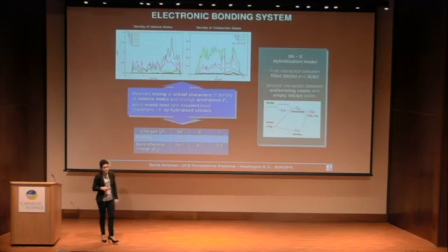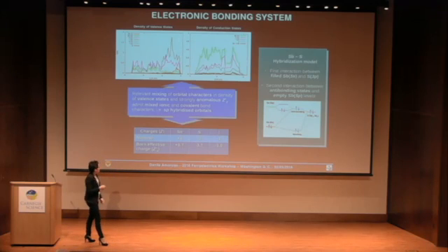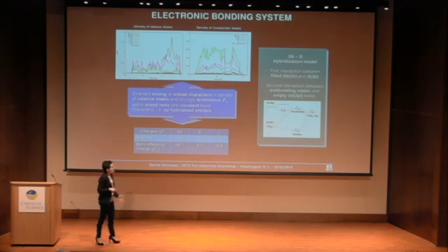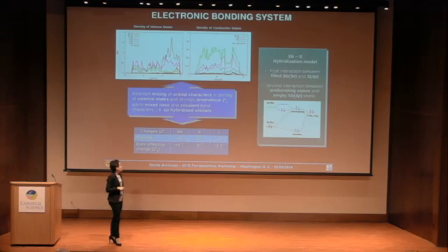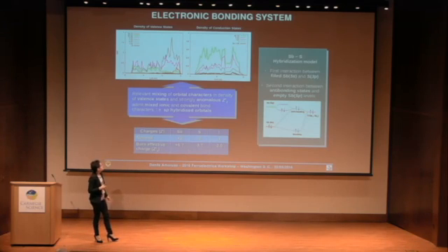We can also try to justify the electronic bonding system by recalling the mixing of orbital characters in the density of states, but also by taking a look at the values of the Born effective charge, which indeed are very anomalous compared to the nominal values. That means that a strong covalency in the bond character is present, and so we can again talk about an sp hybridization model that occurs between antimony and sulfur.